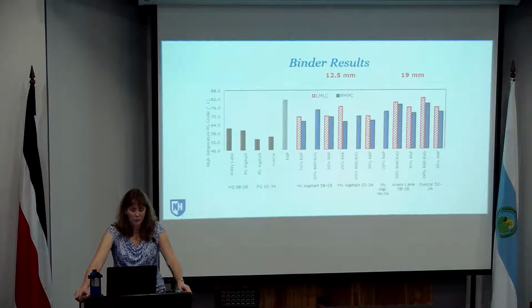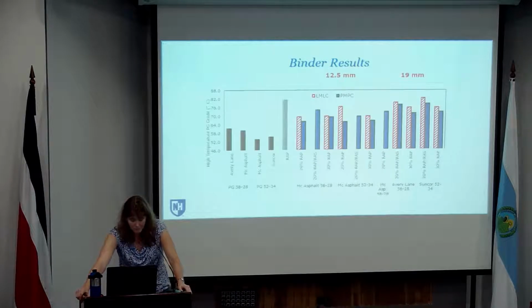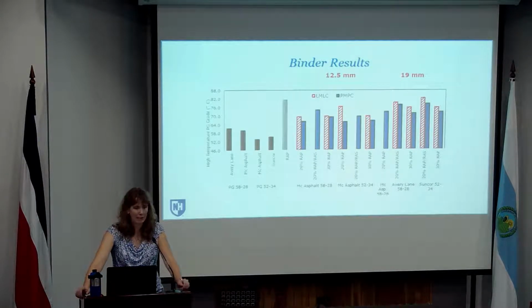Looking at the results from the 19 millimeter mixtures, here we've got a couple different sources. And again, we're seeing kind of the same thing. Differences with the wrap to the wrap RAS materials, a little bit of a change with the different content for just the wrap, but still we're seeing stiffer response from those laboratory-produced mixtures than from the plant-produced mixtures. So that's on the high temperature side.